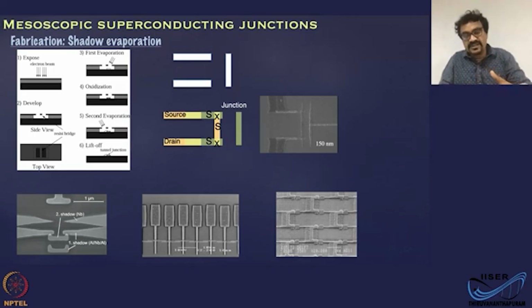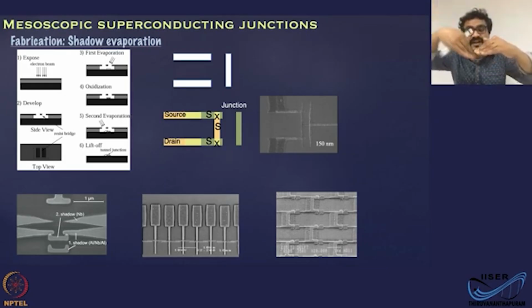Now what you will do next is you would admit some oxygen or mixture of oxygen and some other inert gas into this chamber, which will quickly oxidize the material that you have deposited. The first material normally is almost always aluminum, which is a superconductor, and when you admit oxygen inside the chamber, you will form a thin layer of aluminum oxide. After the formation of the oxide, you will pump out the oxygen, whatever we have put inside the chamber. Then you will do a second evaporation, but that will be from a different angle.